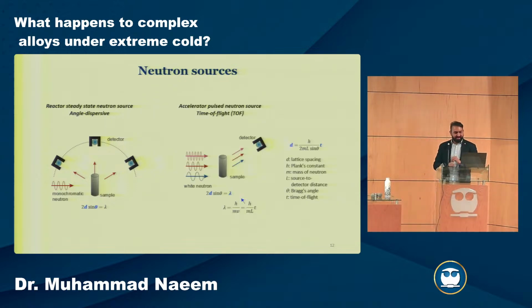Then the second one, which I was mentioning, is spallation source based, which we call pulsed, because it generates a pulse and then there is nothing and then again a pulse, and the kind of operation it has is called time of flight. In this case we don't have one wavelength of neutron, but multiple wavelengths, which we call white beam radiation, which is coming to your sample, interacting with the sample, diffracting, and then we collect the information in a detector. The same Bragg's law applies, but now you have to modify certain things, because here you don't have one single wavelength.